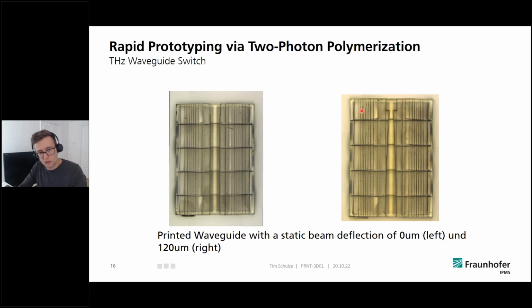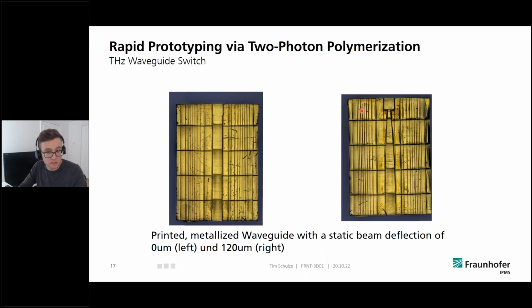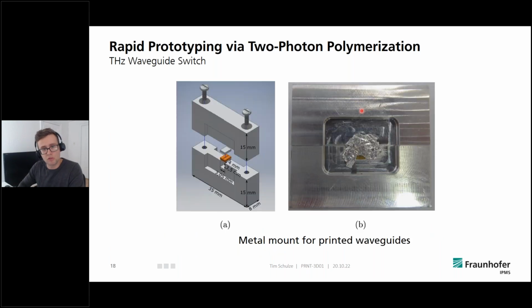Finally, we got our printed object. We metallized it with gold. Gold is really great for metallization of such substrates by sputter coating. And in the end, I put this in a metal holder. And of course, I showed you the waveguide. It's a tube that is enclosed by metallic sidewalls in all four directions. And on top of my printed component, I put another metallic block. And then in the end, it looked like this in my design.